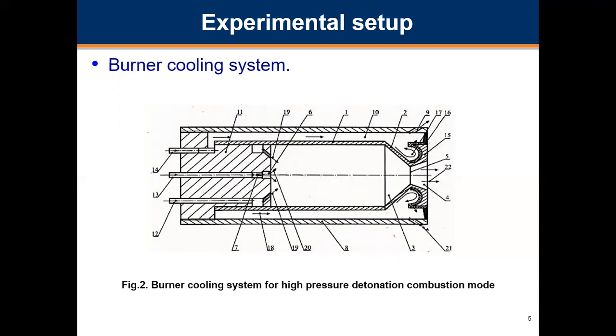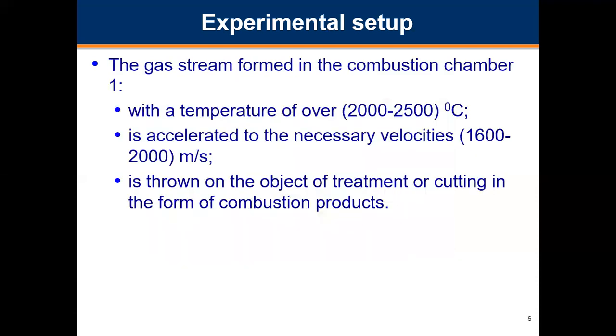The coolant 18 is supplied to the branch pipe 14, leaving the coolant moves in the cooling cavity 10, formed between the shell 8 and the outer walls of the combustion chamber 1 and the nozzle 2, consisting of the confuser 3 and diffuser 4 parts separated by the critical section 5. The gas stream formed in the combustion chamber 1 with a temperature over 2000 to 2500 degrees Celsius is accelerated to the necessary velocities of 1600 to 2000 meters per second in the nozzle 2 and is thrown on the object of treatment or cutting in the form of combustion product 22.